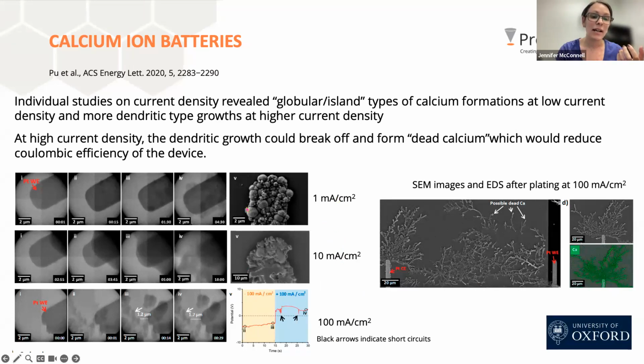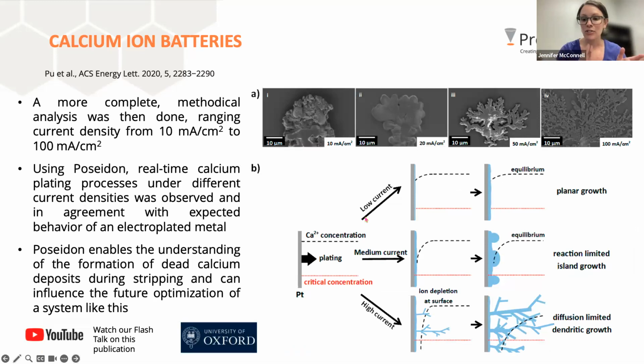What they see is that at lower current densities, you get what the technical term they used was globular or islands, these bulky growths. As you go to higher current densities, you see what you see here. It's more classic dendritic growth, these branches with thin connector pieces that are more likely to break off. So they did a really methodical study to understand, as you change different variables, particularly current density, how that affects the growth of the dendrites and the redissolution.